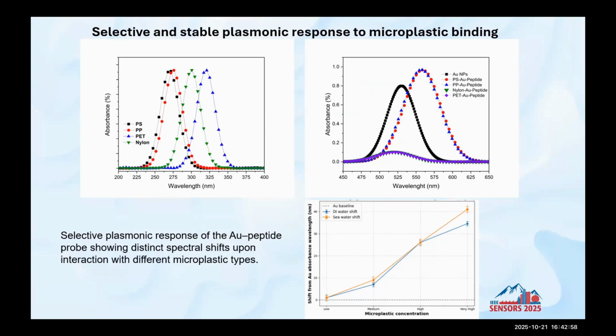All the tests I have explained so far were done in clean water. Now we wanted to see whether all these things can work in real seawater or not. So we repeated all the tests in seawater. As the graph shows, the blue line is the clean water and the orange one is the seawater, and they follow each other in a linear way. So there's a similarity between them. The only difference is that the ionic environment of the sea impacts the absorption, but the whole story is very similar between these two. So it shows the interaction is stable and it works in a real-case scenario.